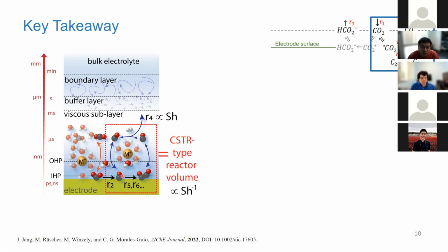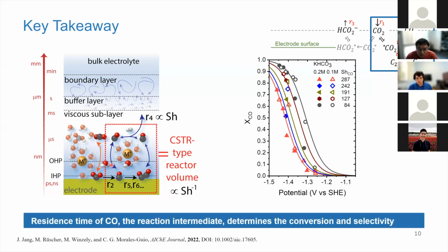So the key message here is that the electrode-electrolyte interface is better described as a continuous stirred tank reactor where you have perfect mixing. And in the remainder of my talk, I will try to provide experimental evidence of why we think that is actually the case. We have done different experiments, and what you will see is that this takes the same shape. For the conversion of that reaction intermediate, carbon monoxide, as you increase the driving force, you follow these different lines. But as you change the mass transport properties of the cell, you can tune the volume of that perfect mixing near the surface of the electrode, and then they fall into different lines.